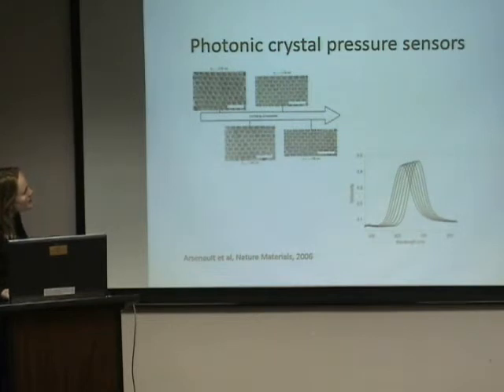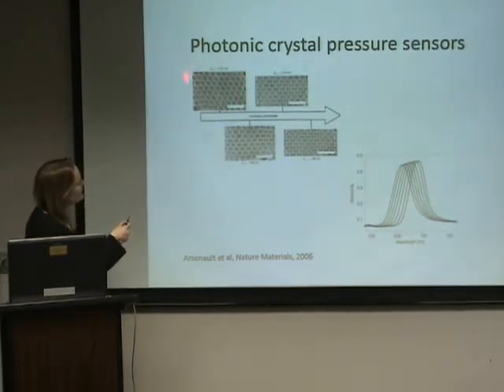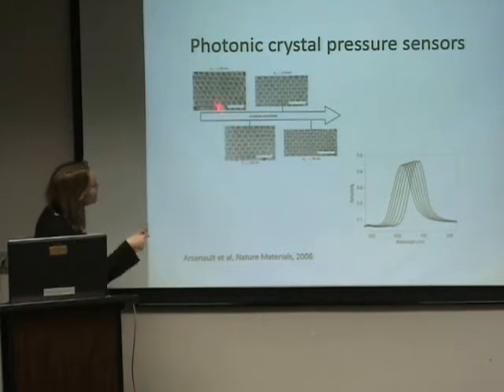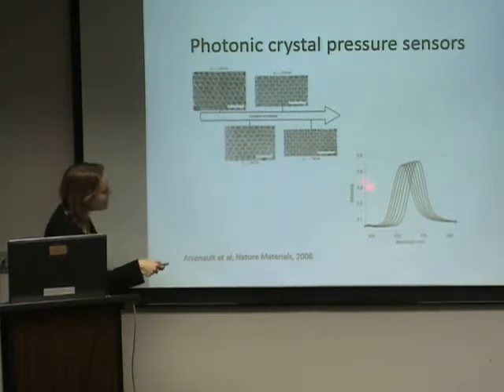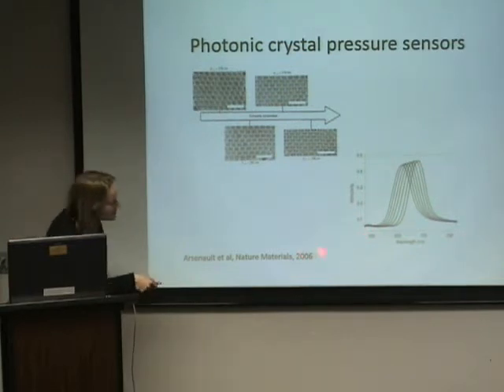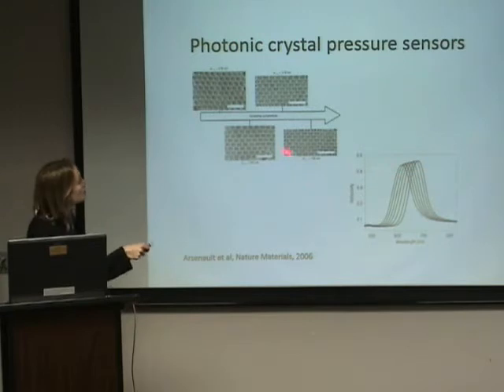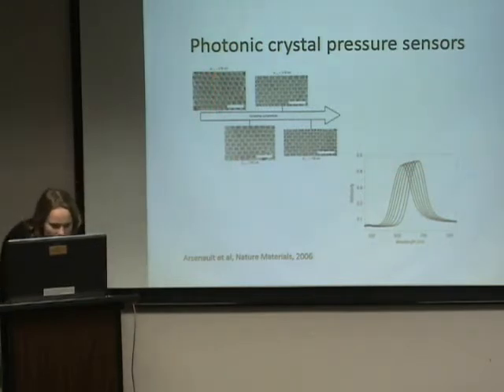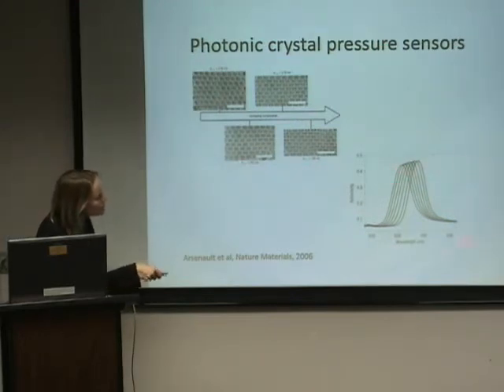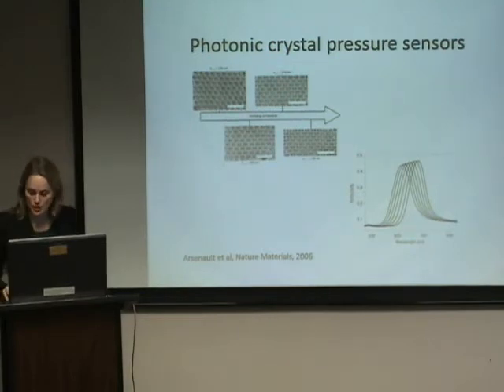Okay, so one example of this from the literature is from this paper in Nature Materials. This was using these photonic crystals as pressure sensors. In this case, they took a 3D material and applied compression. As you go this way, it's a little hard to see, but you see these shrink a little. As they increase the pressure on it, they measure reflection as a function of wavelength. I'm sorry, that's a little fuzzy. And you see the peak shifting over. So if you compress, this says 276 nanometer lattice constant here, and then this went down to 188. So kind of significant shift got you that far, but you could observe the wavelength shift. And this is measured in reflection using a spectrometer.